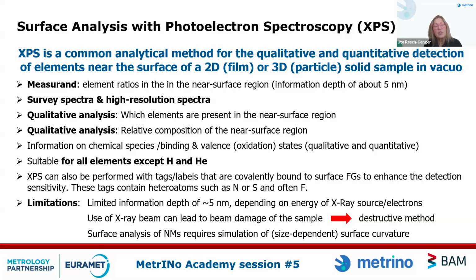Then you have this ratio. You get information on the binding state of your element, the valence, oxidation state, and it's suitable for all elements except hydrogen and helium. So it can also be performed with labels, tags, to increase the sensitivity. There you often use heteroatoms like fluorine, for example. So limitations are the limited information depth. Then when you use X-rays, well, you can have beam damage, so it's a destructive method.